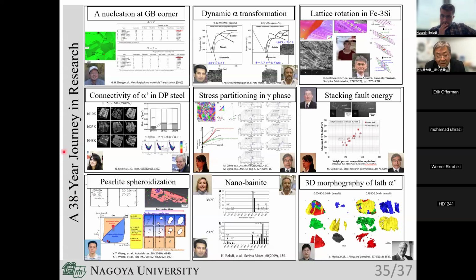And here, we present a method to measure stacking fault energies in high nitrogen austenitic steels by the weak beam method of the TEM. This value is crucial for predicting the deformation mechanism like twinning.